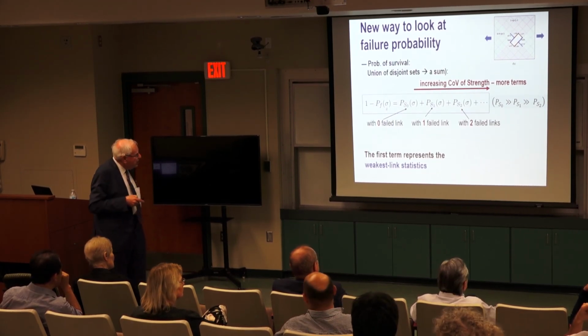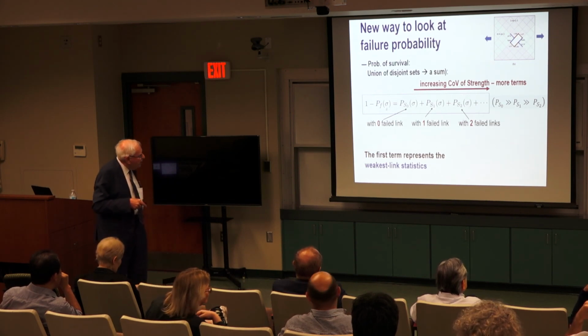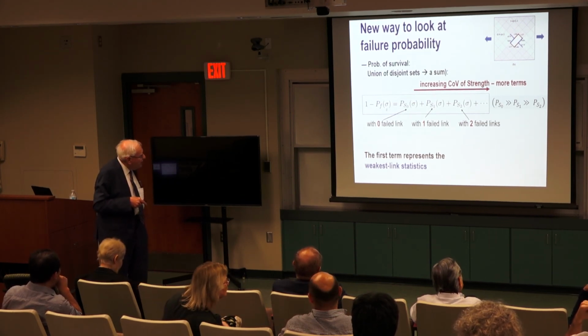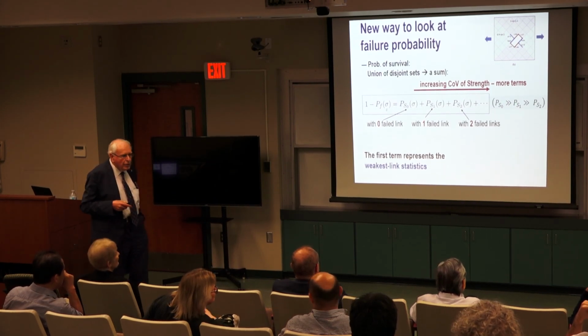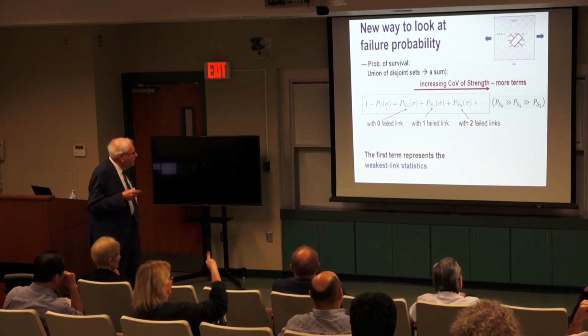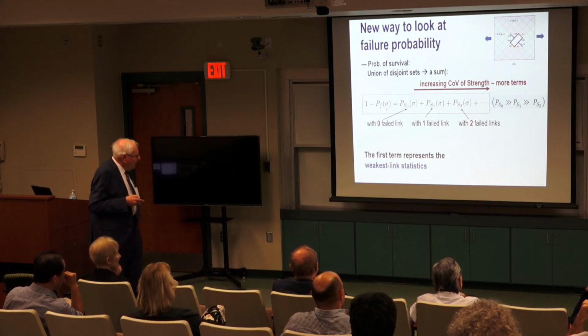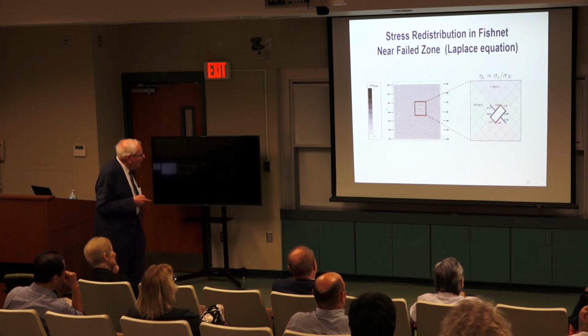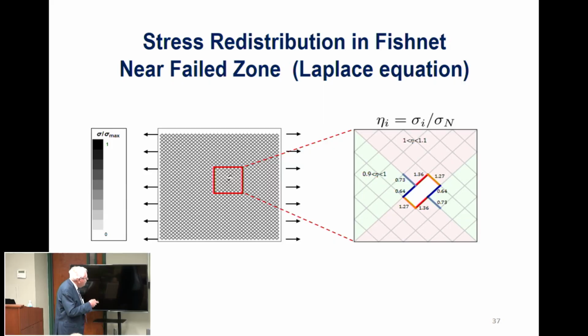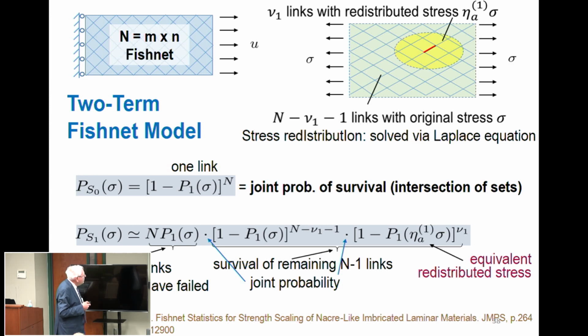Now what is interesting about this sum is that these terms decrease rapidly. There are many failures with first link, second, this is much bigger than that, and you really don't need more than about 4 terms. Even 3 terms is enough. So that can be calculated quite well. So the calculation involves some redistribution, which I mentioned here already. If one link fails, this is higher stress, then it decays. We replace this with a continuum, which goes to the Laplace equation. We calculate continuous redistribution and then project it into the mesh. So we get the calculations.